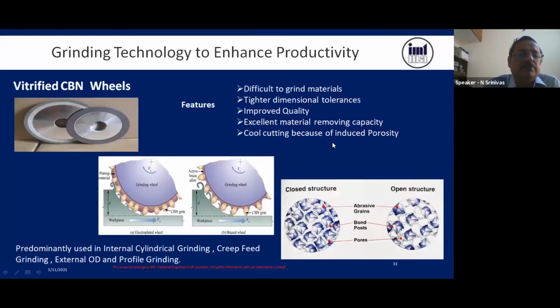And this is the vitrified CBN bond. What we have used here is vitrified. We use it for difficult to grind materials, tighter dimensional tolerance, improved quality, excellent metal removing capacity, and cool cutting with some induced porosity. We use it mostly whenever tight tolerances are required. This vitrified wheel costs more, and a high cutting speed is required in the machine, like 45 meters per second minimum.